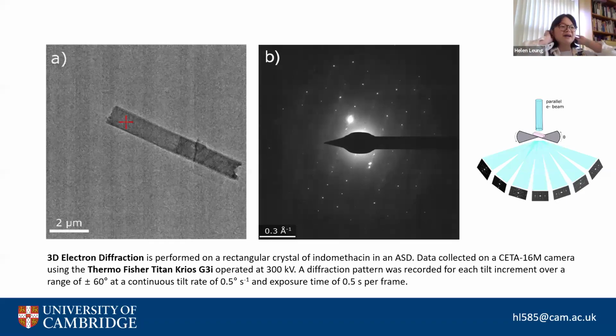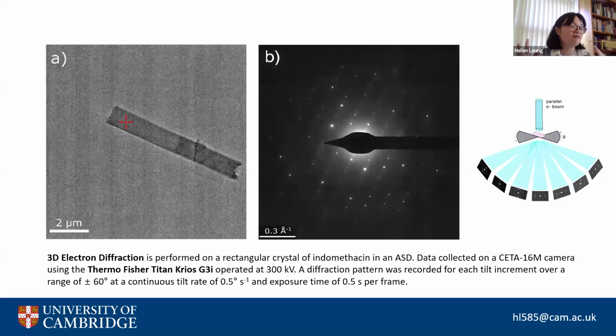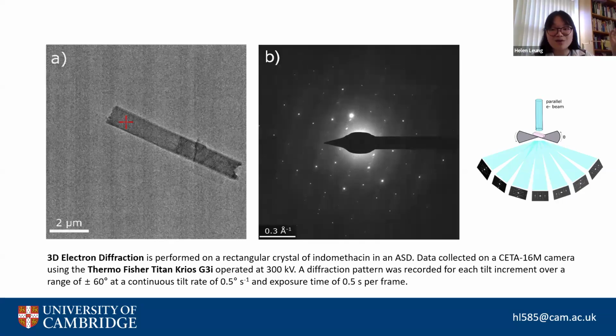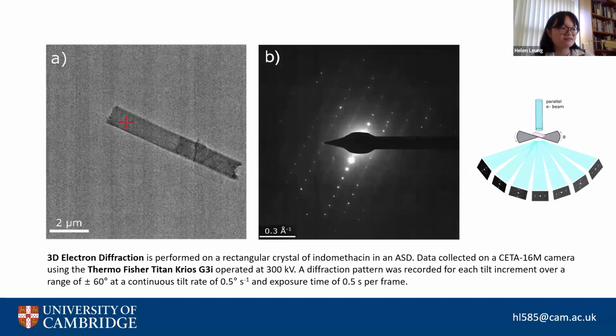So we applied 3D electron diffraction firstly to our amorphous solid dispersion, looking at crystals within the powder, within this formulation, to see what crystal structures we had. And we found a new form of indomethacin, whose unit cell didn't match essentially any of the unit cells that had been seen before. And this was done at cryogenic temperatures on a cryo-EM, essentially. And we can see the crystal there, so you can see the size of the crystal we collected from, and you can see the tilt series as well.